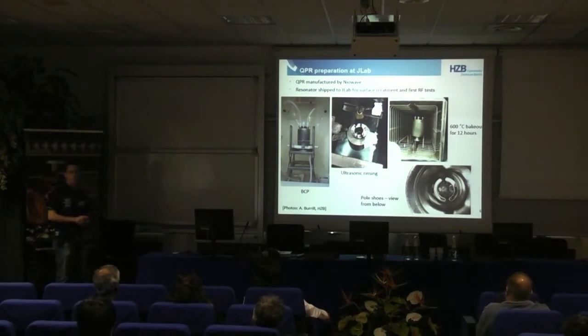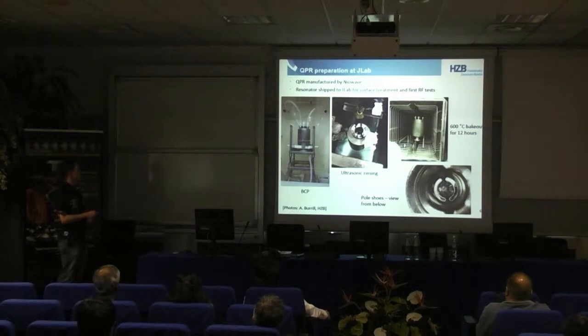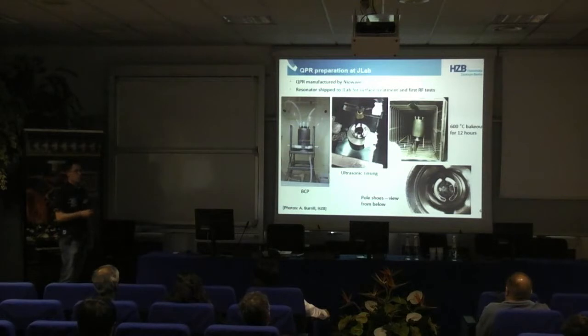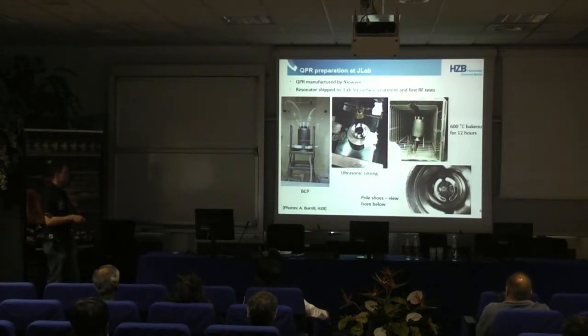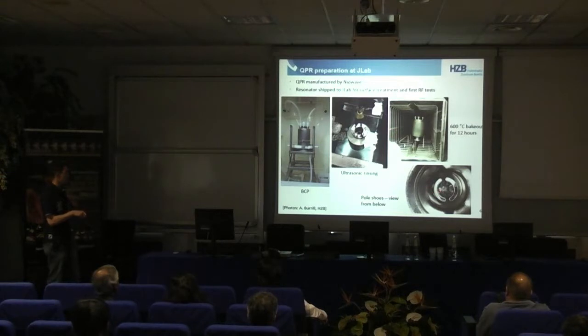The resonator for HZB is in production — actually, production is already finished. It was shipped to JLAB for surface treatment. We already received a standard cavity procedure with BCP, ultrasonic rinsing, and a bake-out. You see here a picture of the sample on these pole shoes, with the quadrupole rods visible from the top side.